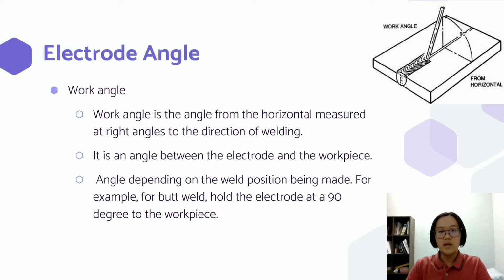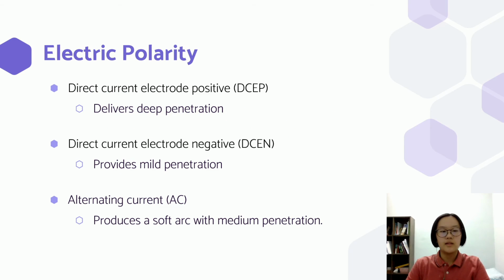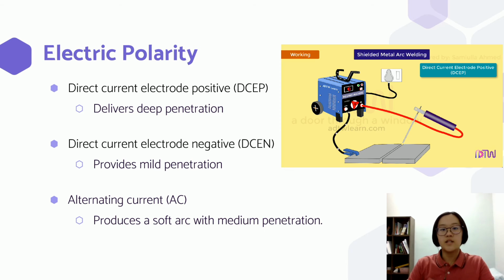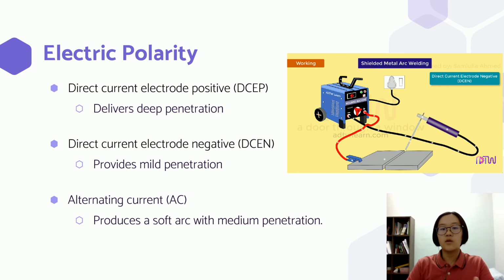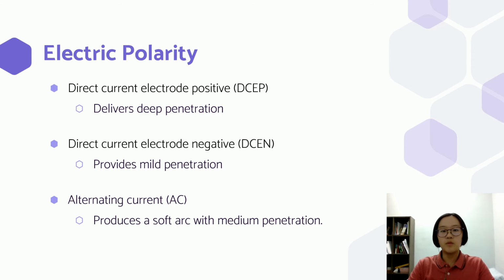Different weld positions may have different work angle. For example, butt weld had a work angle of 90 degrees. There are 3 types of electric polarity, which is direct current electrode positive, direct current electrode negative, and alternating current. For DCEP, the electron flows from the workpiece to the electrode, while for DCEN, the electrons flow from the electrode to the workpiece. This result to DCEP will provide a deep penetration, while DCEN will provide a mild penetration.